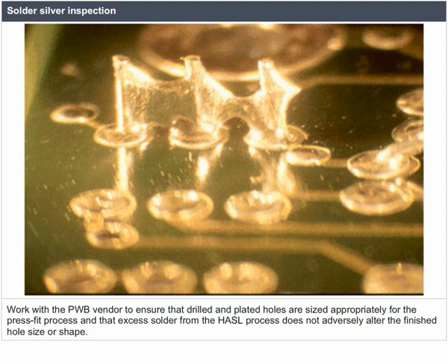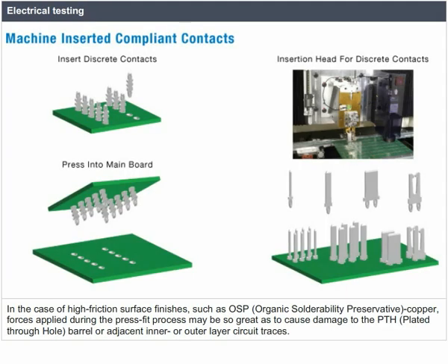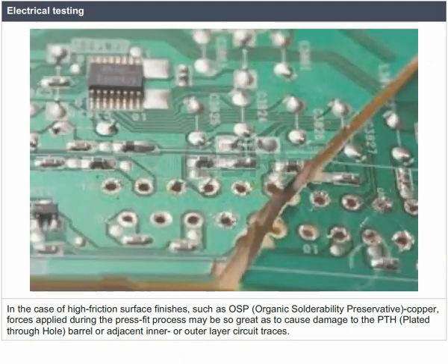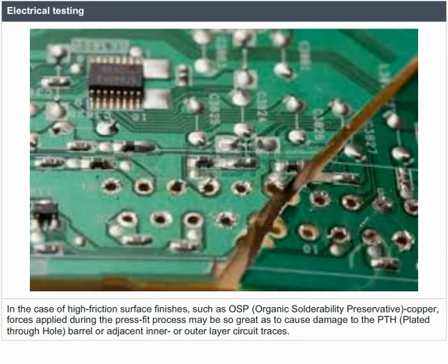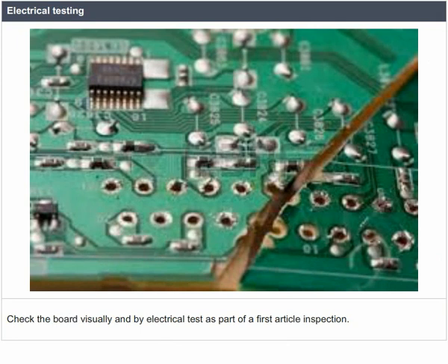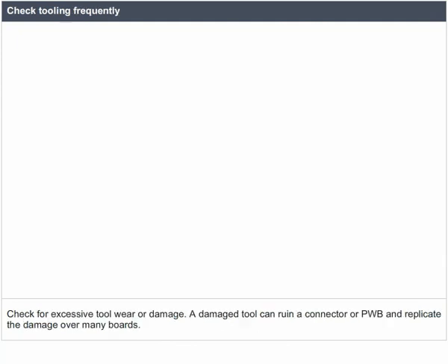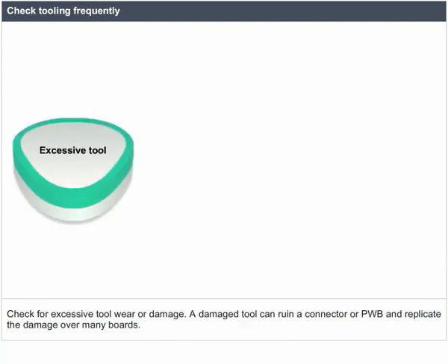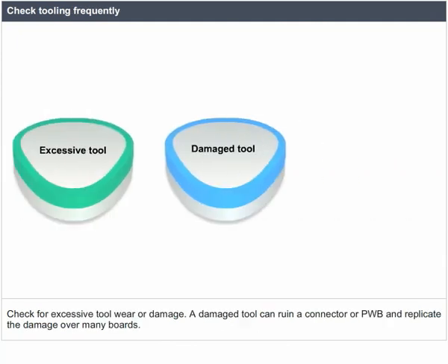Electrical testing. In the case of high-friction surface finishes, such as OSP, organic solderability preservative, copper, forces applied during the press-fit process may be so great as to cause damage to the PTH, plated through-hole barrel, or adjacent inner or outer layer circuit traces. Check the board visually and by electrical test as part of the first article inspection. Check tooling frequently. Check for excessive tool wear or damage. A damaged tool can ruin a connector or PWB and replicate the damage over many boards.